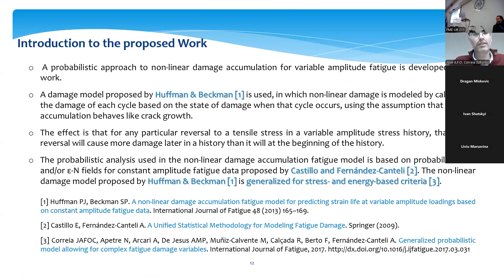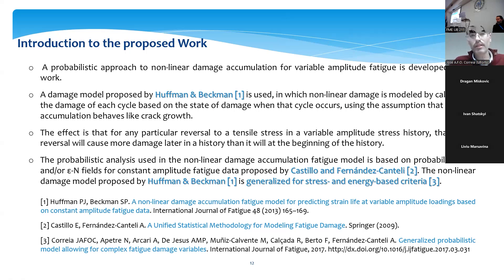According to this previous introduction, a new approach to non-linear damage accumulation for variable amplitude fatigue is developed in this research work. We will use the non-linear effective damage rule proposed by Huffman and Beckmann, which uses the assumption that damage accumulation behaves like crack growth. This approach can be applied for the stress parameter, but also for the strain parameter, energy parameter, and considering uniaxial and multi-axial loading conditions.